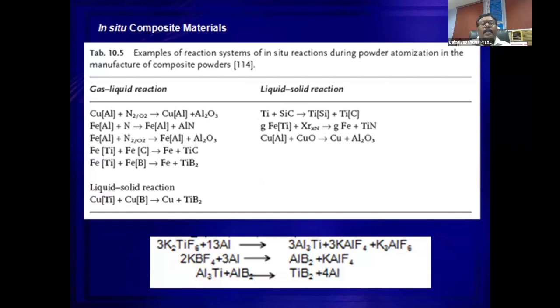So for these ex-situ reactions, the problems of homogeneous distribution and interface bonding mechanism can be eliminated by developing the same reinforcements by in situ reactions. In the in situ reactions, you have a gas-liquid reaction and a liquid-solid reaction. One reaction that we have demonstrated is the liquid-solid reaction. We take solid precursors K2TiF6 and KBF4, with aluminum as the matrix material, and these reactions will produce TiB2 ceramic particles in it. So this is the procedure.